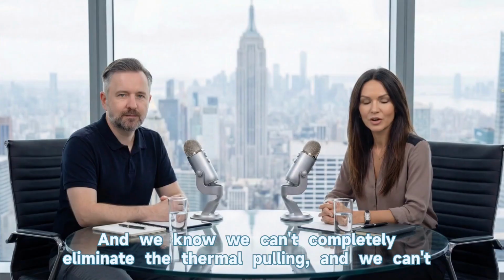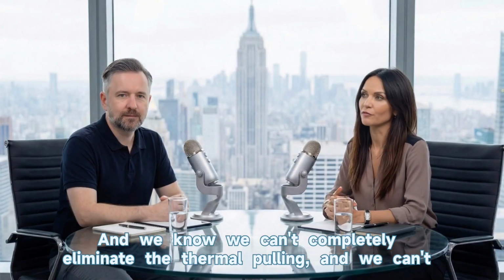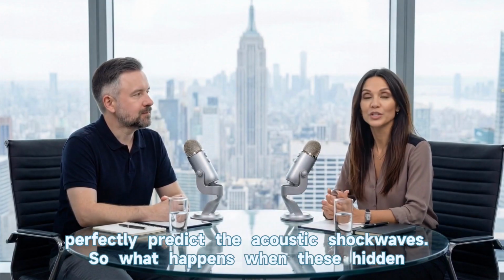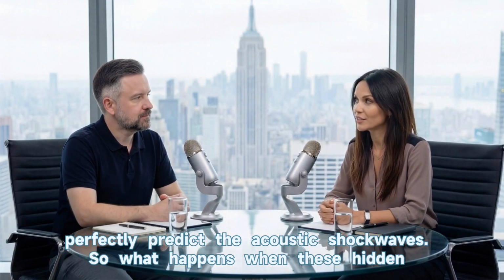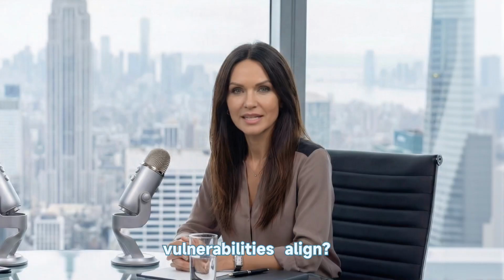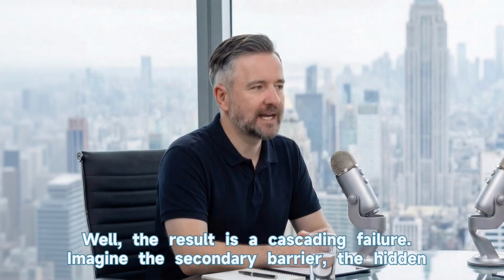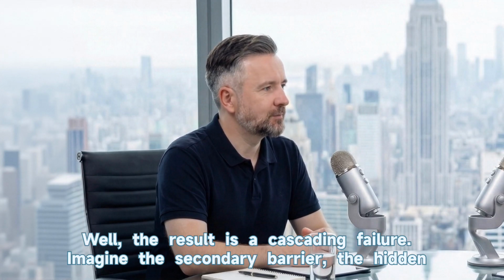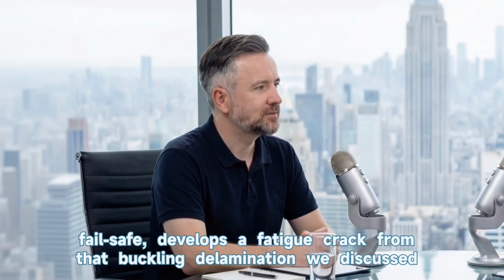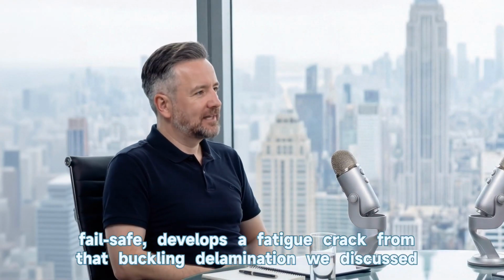That's right. And we know we can't completely eliminate the thermal pulling, and we can't perfectly predict the acoustic shock waves. So what happens when these hidden vulnerabilities align? Well, the result is a cascading failure. Imagine the secondary barrier, the hidden failsafe, develops a fatigue crack from that buckling delamination we discussed earlier.